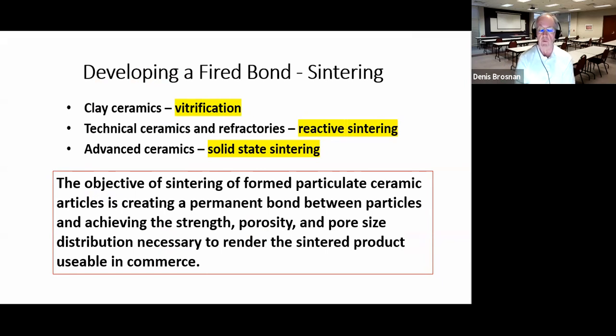What we want to do is develop what's called a fired bond through the process of sintering in firing the ceramic. So you've heard about sintering before in earlier courses, but I want to expand on the idea of sintering to make sure that you understand there are at least 3 types of sintering that we will talk about in the course. With clay ceramics, we talk about vitrification. Vitrification forms glass within the ceramic at elevated temperature, as I just mentioned in the case of bricks. The glass solidifies, becomes rigid, and provides the major source of bonding within the ceramic once it's been processed.